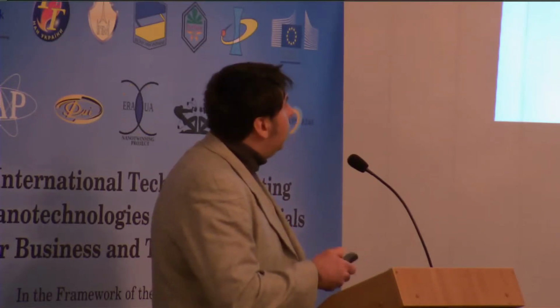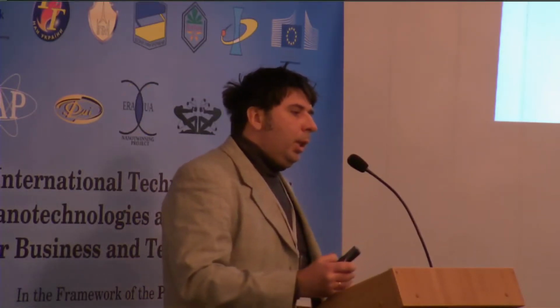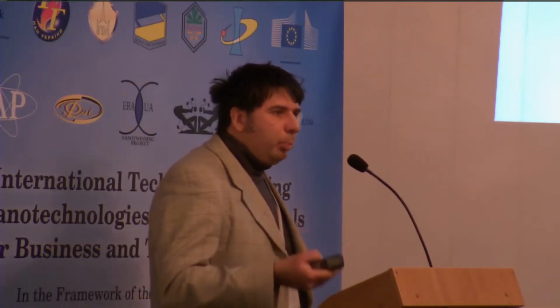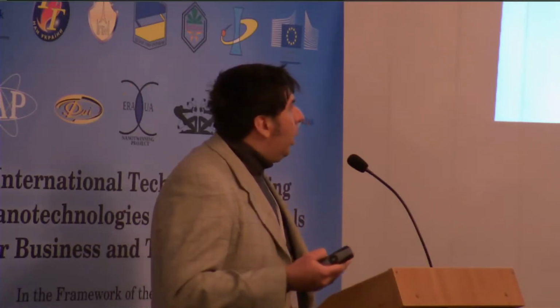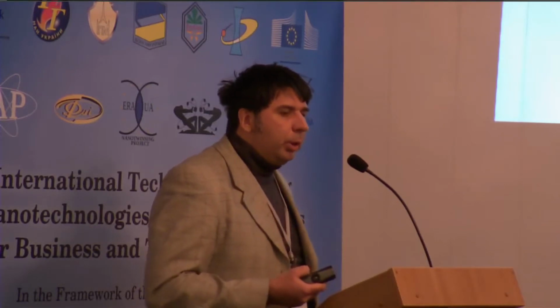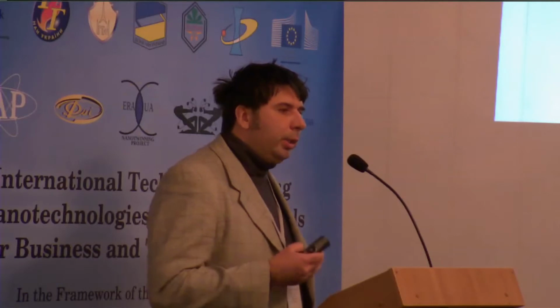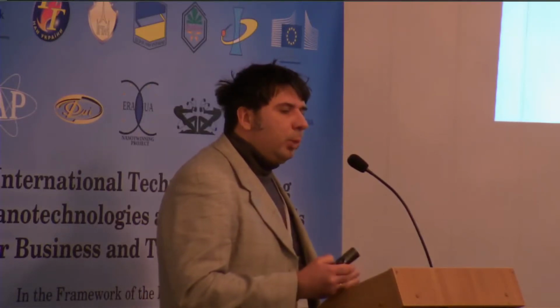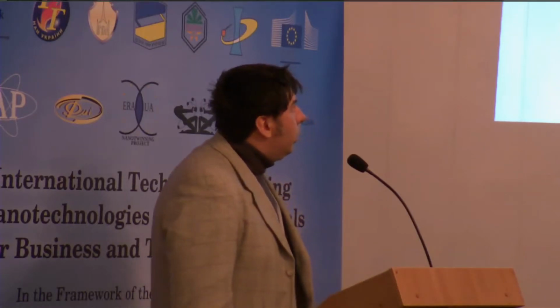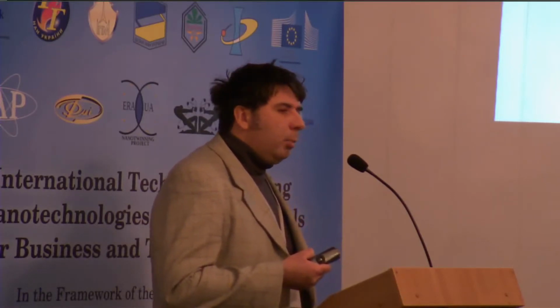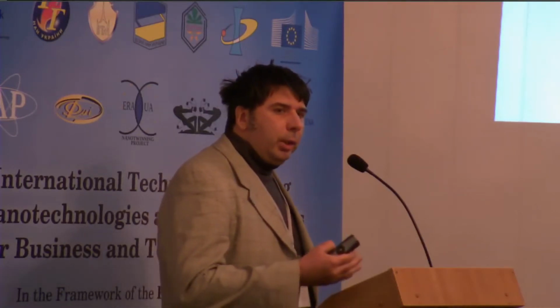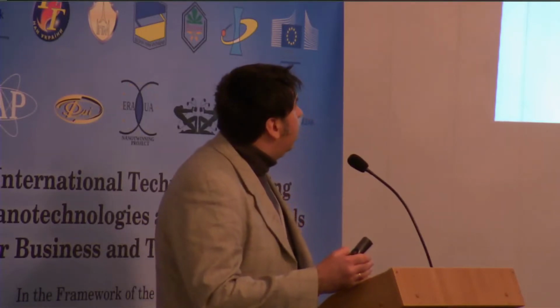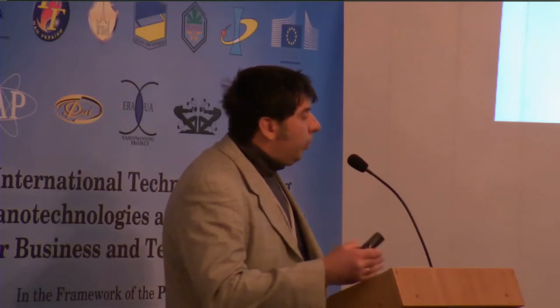On the other side, we tested rate control sintering technology. It could be easily implemented on existing equipment, on existing facilities. Only gas, vacuum, high temperature furnaces are needed to consolidate nanopowders. But this technology is very sensitive to the quality of nanopowders. If we change suppliers, or if the supplier changes some particle size or chemical content of nanopowders, we have to recalculate the schedule. Maybe we have to make some preliminary operation to obtain nanoceramics with guaranteed properties.